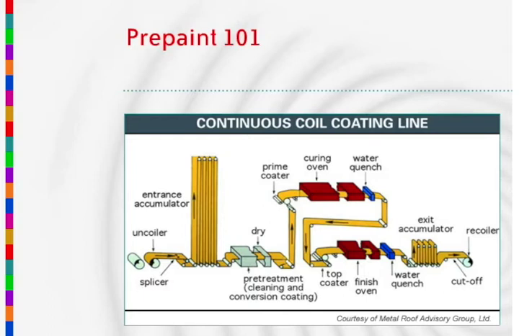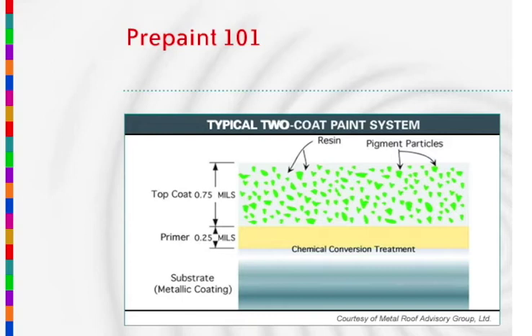The processes of cleaning and pre-treating the metal by chemical conversion are critical steps that make the surface free of imperfections and suitable for maximum primer adhesion and corrosion protection. Primer is applied evenly, edge to edge, on one or both sides of the strip, cured in a gas-fired oven and cooled. Modern primers are based on polyester, polyurethane, and acrylic waterborne chemistries, and are used to provide maximum adhesion of the top coat. The top coat is applied over the primer, oven cured, and the strip is cooled to room temperature. At the end of the line, the coated metal is rewound and wrapped for shipping.